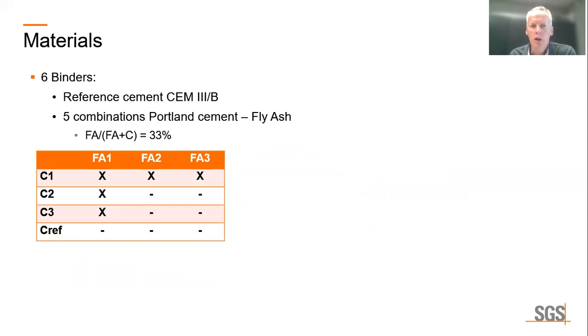For the investigation, we have used 6 different types of binder. One is the reference cement with CEM III/B, and the other 5 are combinations with Portland cement and fly ash. The fly ash content is always 1/3 of the total weight of cement and fly ash. And in this table, we show the different combinations that we have investigated.